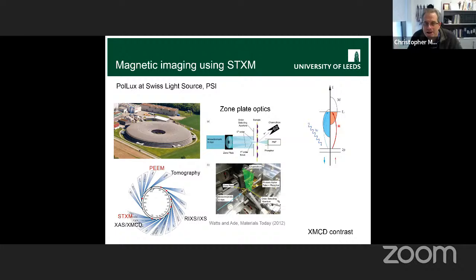And so what that means is that for the handedness of the light that picks out spin up, you'll get stronger absorption, and that means less light falls on your detector. So what's important is the relationship between the helicity of the photon and the component of the magnetization along the beam direction, which is the film normal in our case. And if you scan the energy, here's an example for nickel. You pick out the L3 and L2 X-ray edges, which correspond to these 2p levels, and you can see there's a difference between positive and negative circular light, the level of absorption that you get.